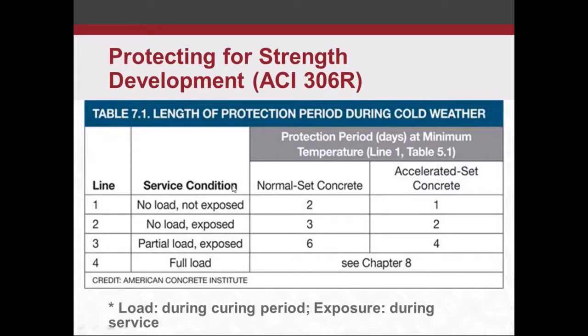It doesn't explicitly say that in the table, but when you read through the ACI document, that's what it states. Now this exposure is exposure during the service period. So the no load is during the curing period, and the exposure is during the service period. So normal set concrete, if we don't have a load on it during the curing period, during the first 28 days, and it's not exposed to freeze thaw in service, that would be something like maybe a foundation wall, if you're not going to start putting up column loads or wall loads along the foundation, and the foundation is below the frost level.